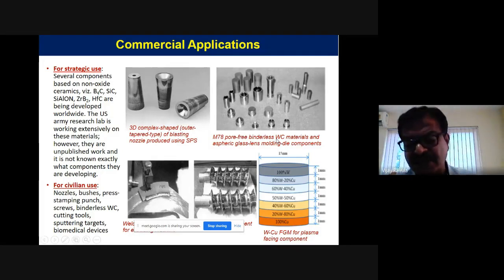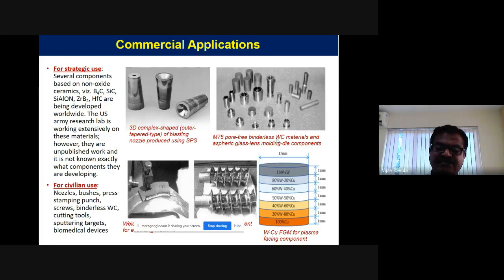Sintering of tungsten carbide is a big problem because it needs very high temperatures to get a good density. So people use a binder like cobalt, or even nickel, so they use liquid phase sintering. Because the binder is a lower strength material, the overall strength of the tungsten carbide goes down. But when we use spark plasma sintering, we don't have to use any binder. We can use tungsten carbide directly and make these components. Typically, you can also make nozzles, bushes, press stamping punches, sputtering targets, even biomedical devices, and functionally graded materials using this process.